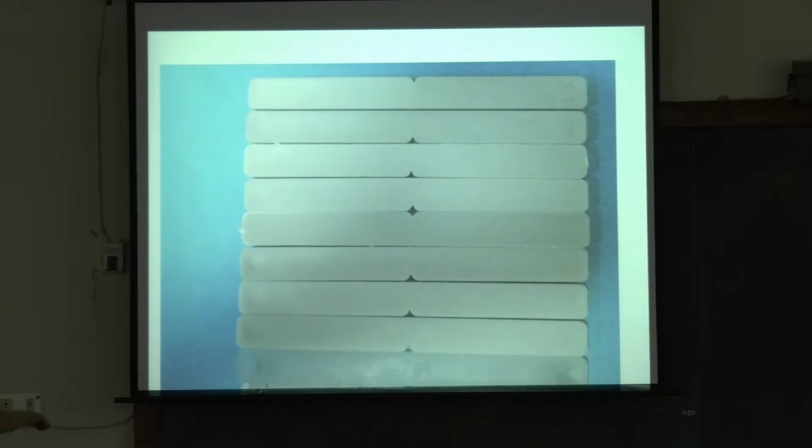So this is the same samples. This is the polypropylene without any name. And then I said, put them in any order. So there's a mix. You cannot say which one has 5% or which one has 10%, which one 80% or 60%, but they all look the same. Can you see that? So irrespective of 5 to 80%, it looks very white.